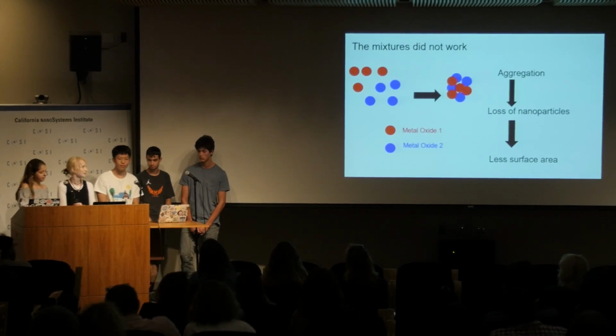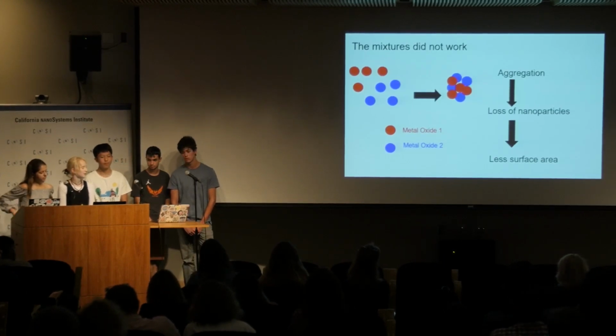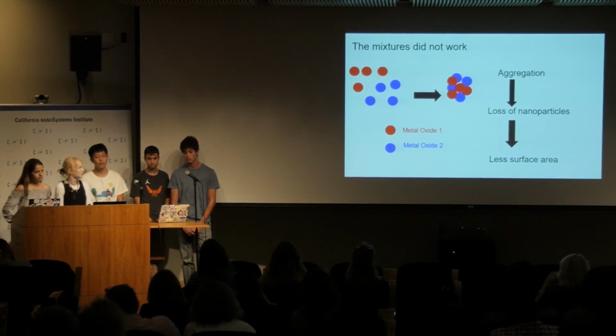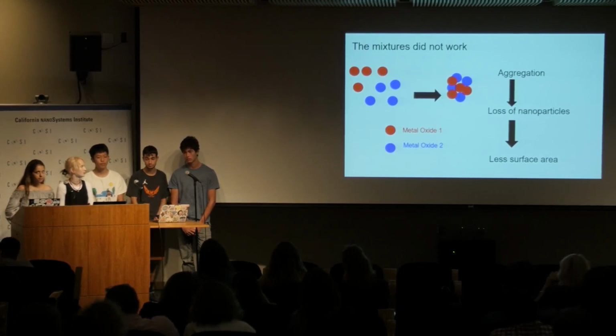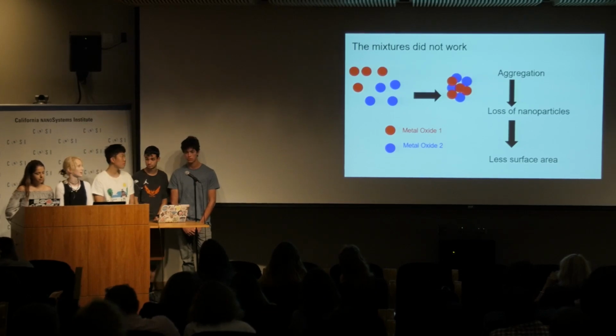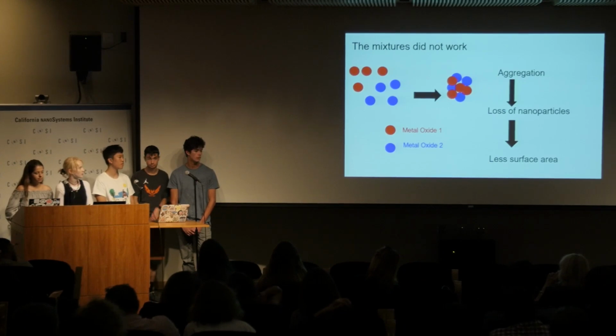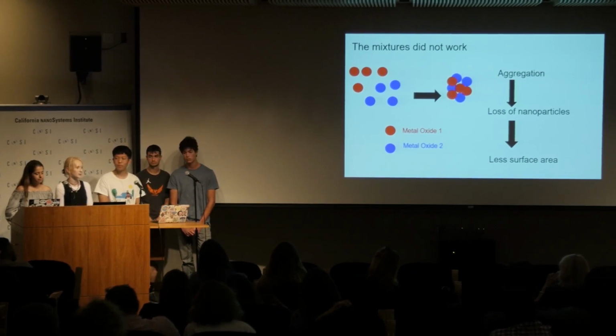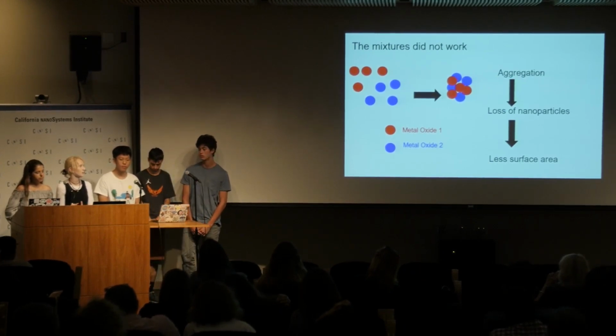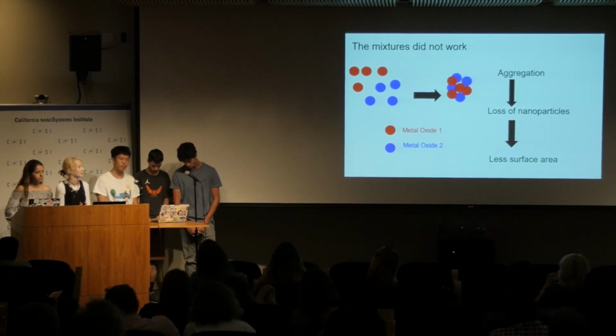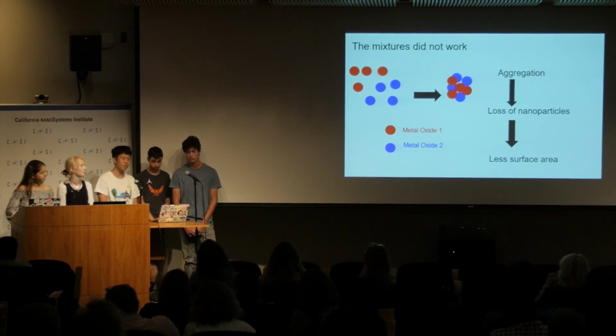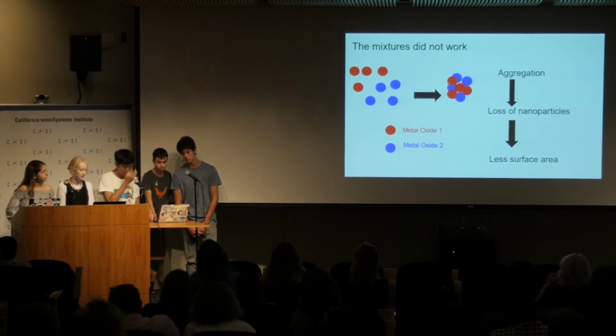So the main reason why we think that the mixtures didn't work and that the layers yielded a much higher result is due to aggregation. So basically, the metal oxides on their own are in their nanoparticle state and size, which gives them their large surface area property. And when you mix the two together, it's very possible that they clump together, which is aggregation. And when you aggregate, there's a loss of the nanoparticles, so now they're at the micro level, and there's less surface area due to that. And with less surface area, less dye is absorbed, and then fewer electrons go through the circuit.